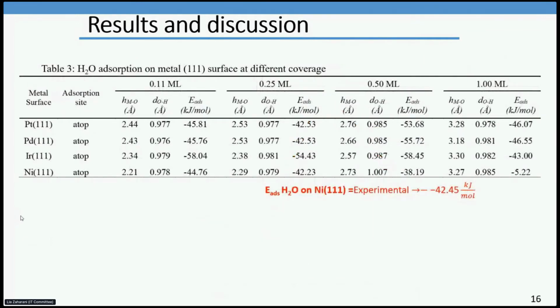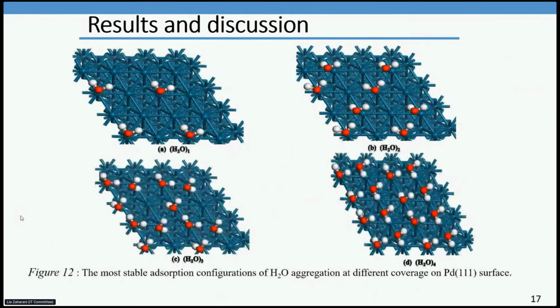This table shows the water adsorption on the metal surface at different coverage. Water adsorption on the nickel (111) surface favors adsorption at the atop site, having adsorption energy of minus 44.76 and minus 42.23 at coverage of 0.11 and 0.25, which agrees with the experimental value of minus 42.45. So it was observed that the water molecule has the strongest interaction with the iridium (111) surface. This figure shows the most stable adsorption configuration of water aggregation at different coverage on the palladium (111) surface.